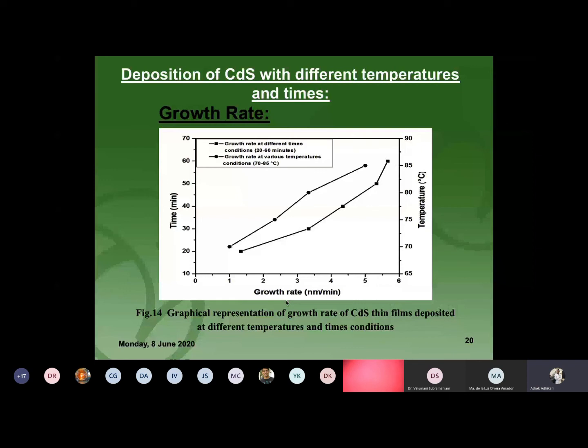So the minimum growth rate is around 1 nanometer per minute at lower conditions, and more than 5 nanometers per minute growth rate observed at higher temperature, around 85 degrees Celsius, and time 60 minutes.